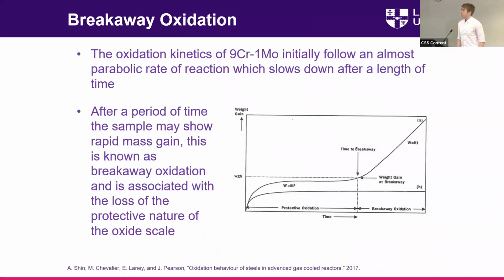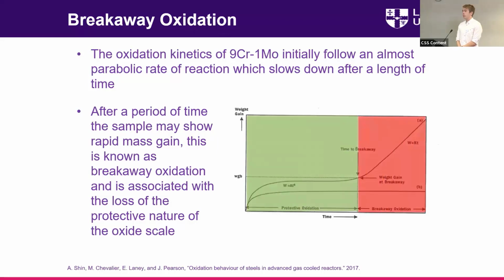One of the things which EDF Energy are interested in is the oxidation kinetics. Initially, when exposed, it follows a parabolic oxide growth, and then this stabilizes out. But after a period of time, it may show some rapid mass gain, and this is known as breakaway oxidation, generally associated with the loss of the protective nature of the oxide scale. There are thought to be many different reasons, with no one really agreeing on what causes it. Some of them range from just geometry effects to carbon saturation within the substrate. So that's one of the key things that was important to try and understand.